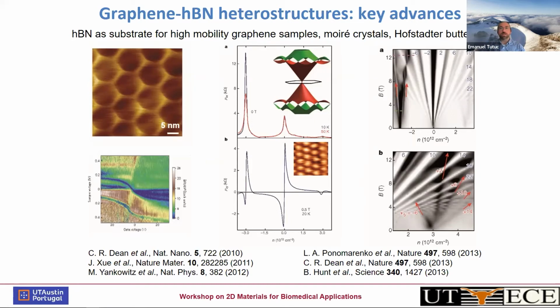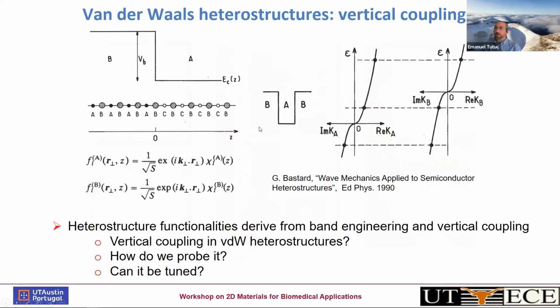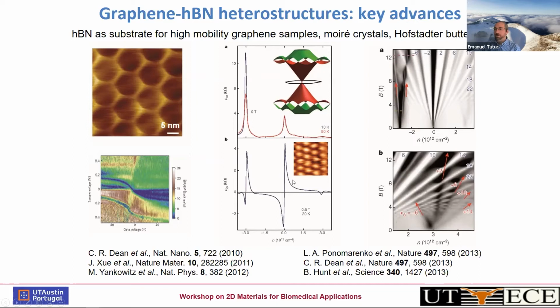The wavelength of the superlattice would effectively create a different Brillouin zone. And the manifestation of that would be that instead of having a single charge neutrality in that heterostructure, there would be replicas of this. You could see here maxima in resistance as a function of a gate bias in this particular data, and that has to do with this restructuring of the energy momentum dispersion. And in magnetic fields, there was a very compelling demonstration of something called the Hofstadter butterfly that probes the fractal nature of the energy levels of electrons in a periodic potential combined with a strong magnetic field.